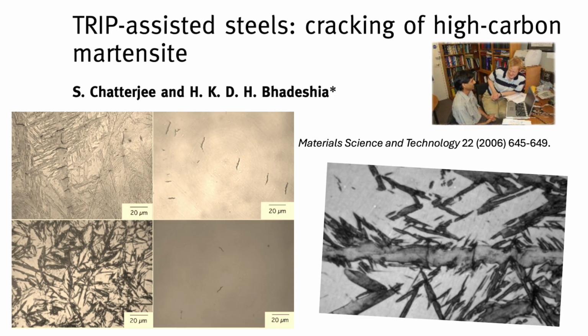Okay, and the fine grain samples, the ones from 950 C. That was the clincher. In the sample with the 25 micron austenite grains, the resulting martensite plates were obviously much smaller, and crucially, they were essentially free of any visible cracks. No cracks at all. None that they could see in the optical microscope. The fine scale prevented the cracking.